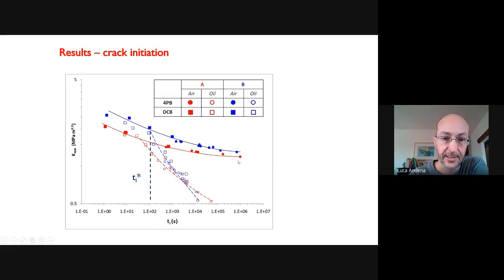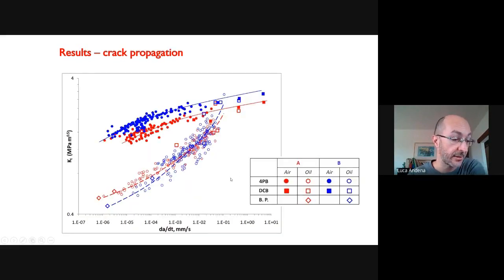If you wait more, typically with lower K, then the effect of the environment will be more and more important. In propagation, you see quite similar results with all the data. Of course, in propagation, you have more data points, but the trend is the same, the blue over the red, then the huge effect of the environment after a critical crack propagation speed, so meaning low K values, and you have this inversion. So you expect the material which is ESC resistant to actually perform better for low values of K, which are typical in the applications.